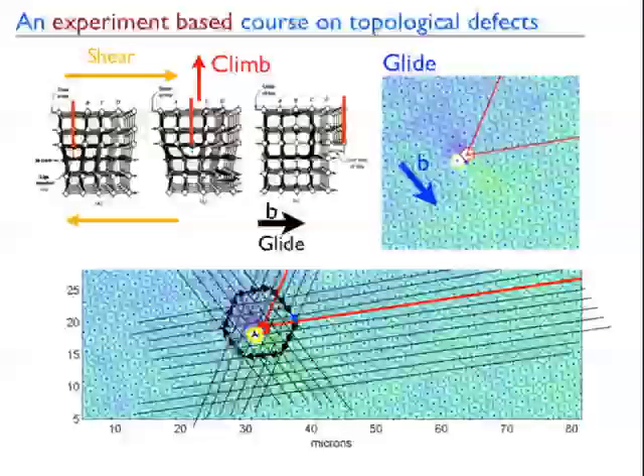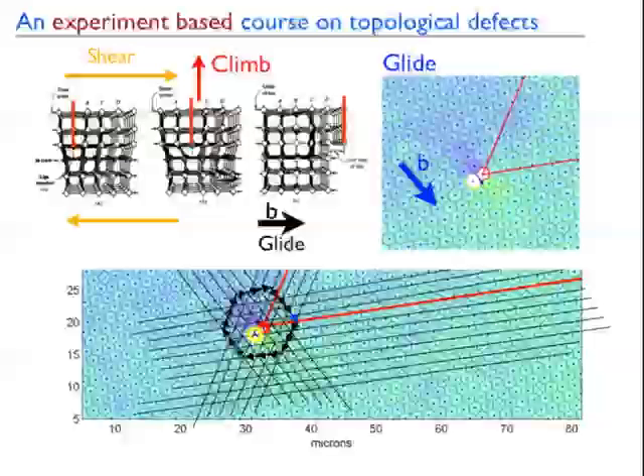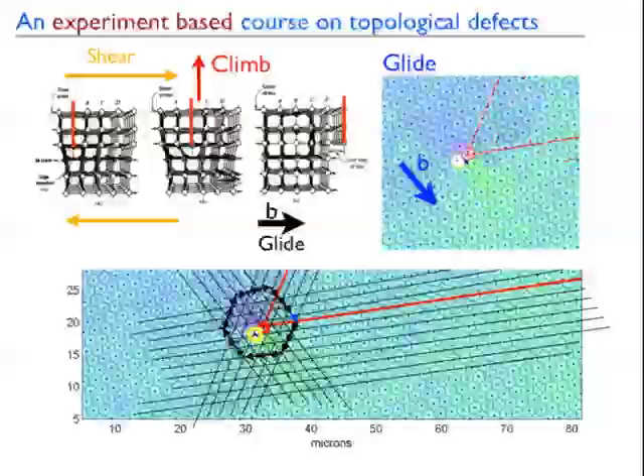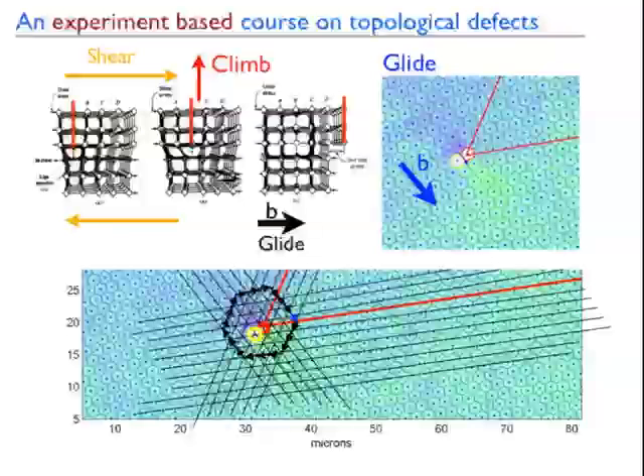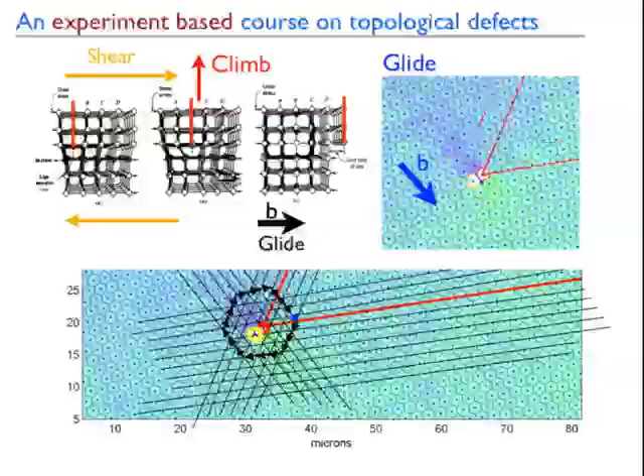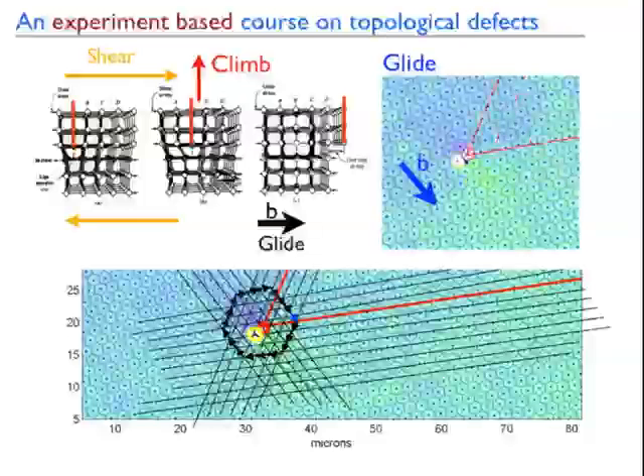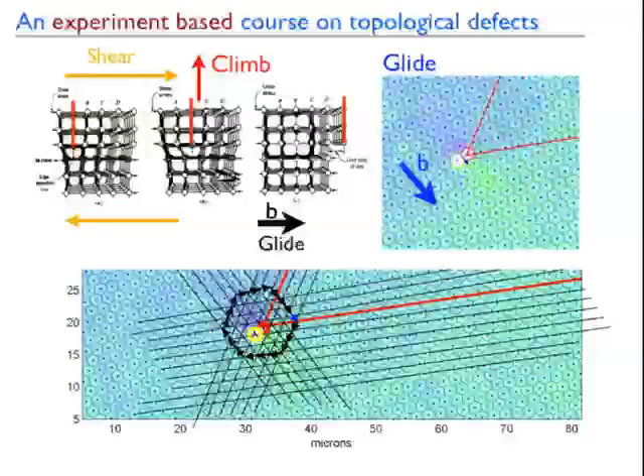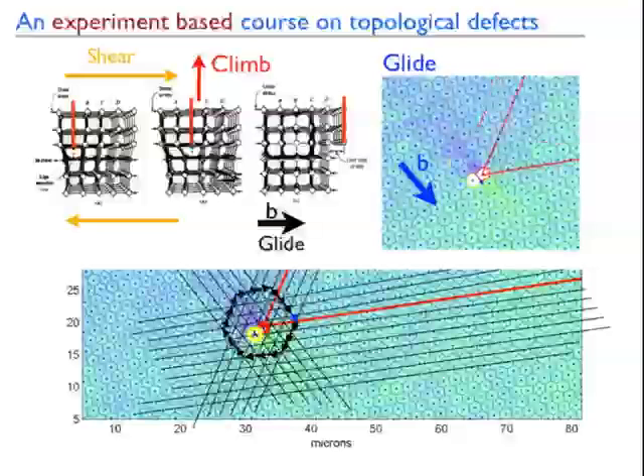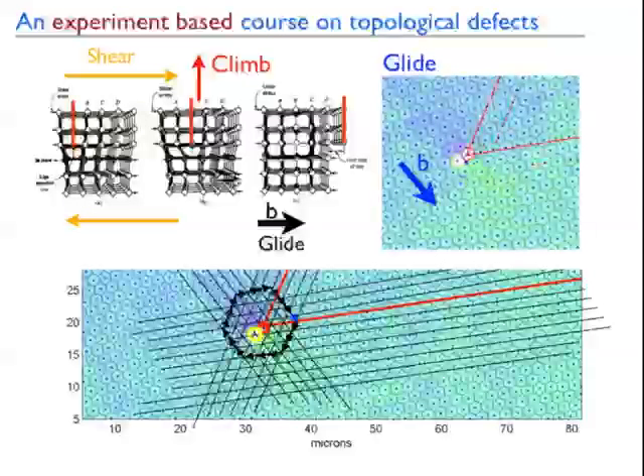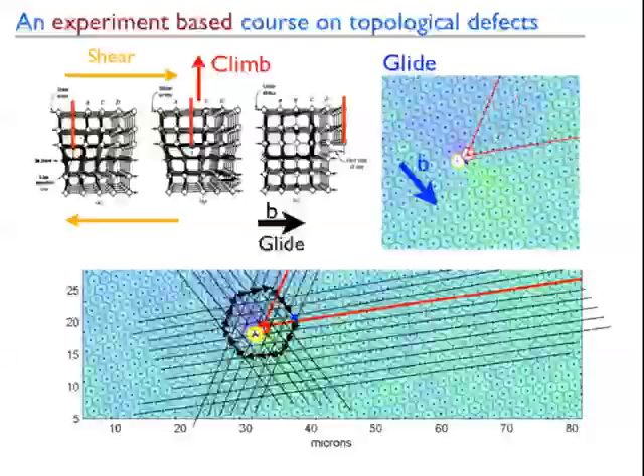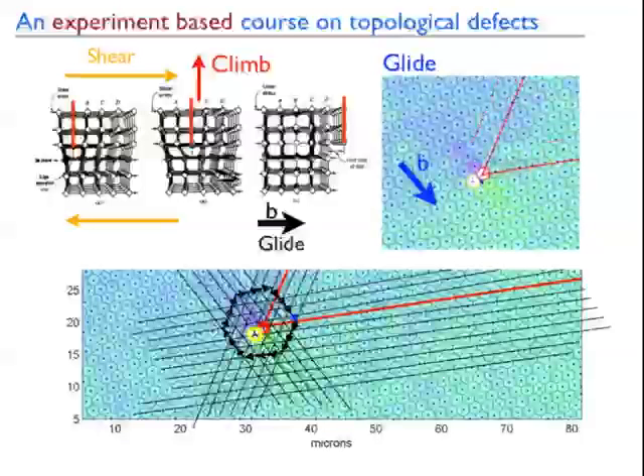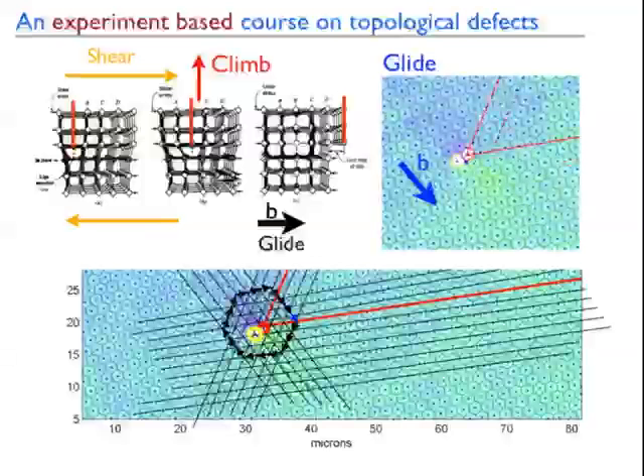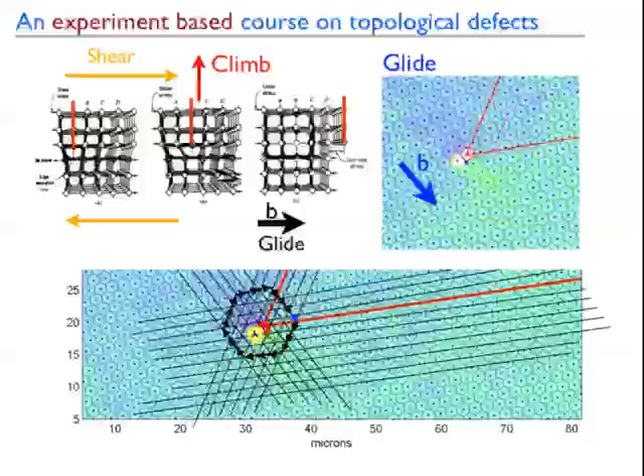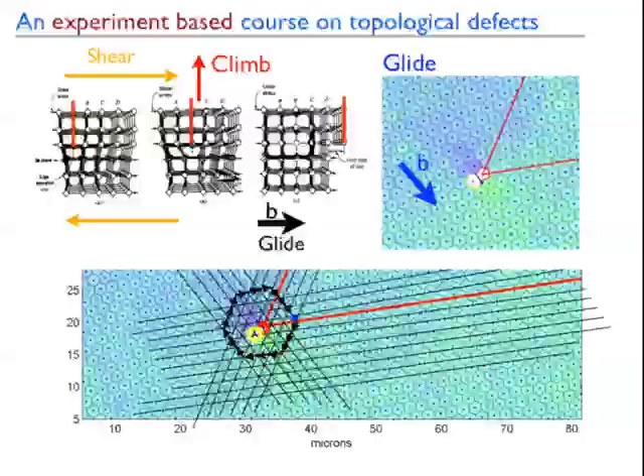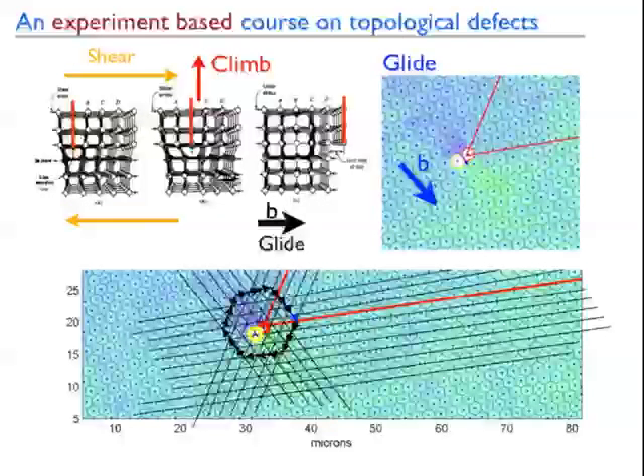They were essentially invented by G.I. Taylor, who's a really great guy, known lots for his hydrodynamics. But what they do is, if you want to shear a crystal, it has shear rigidity. A fluid, you shear it and it just moves and it doesn't come back. A crystal, you shear it and it comes back. But if it has dislocations in it, like this plane over here, then I can shear it like this, and all I do is move this guy over, and further, and I release it, and it doesn't come back. So these dislocations tell you the difference between something that's liquid and something that's solid.